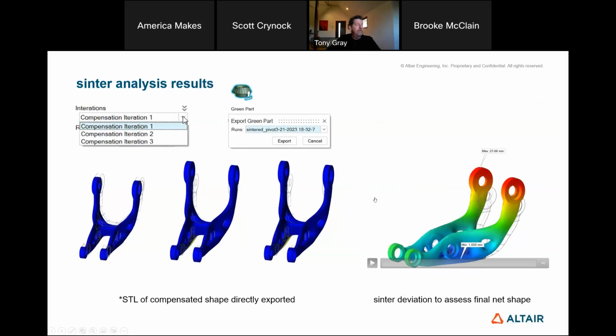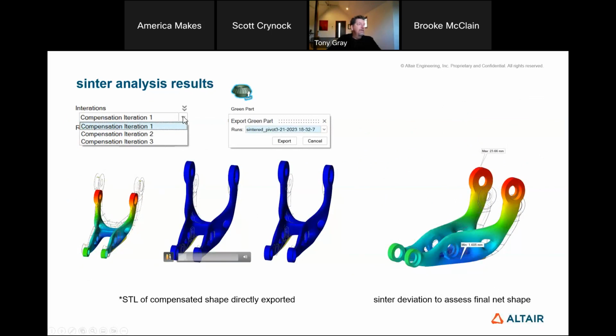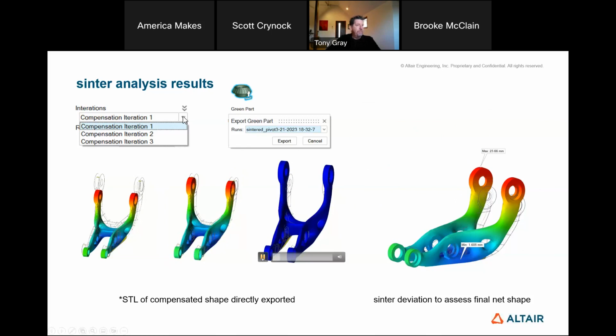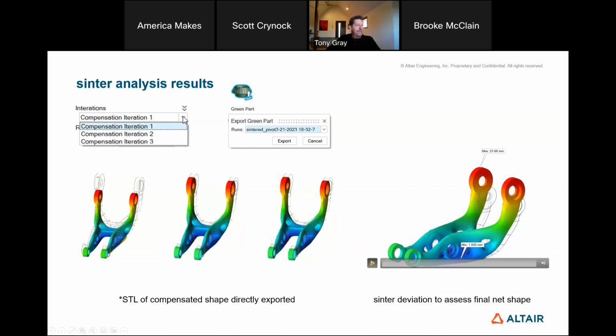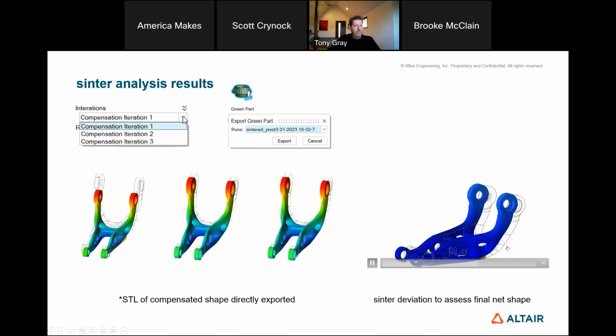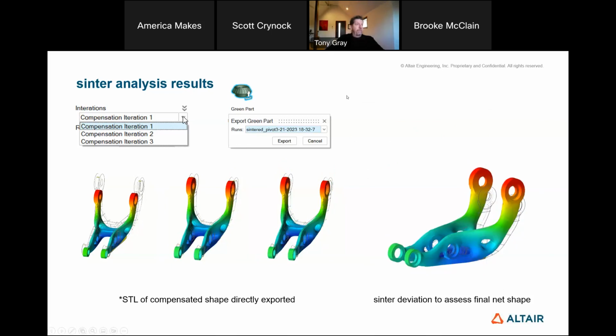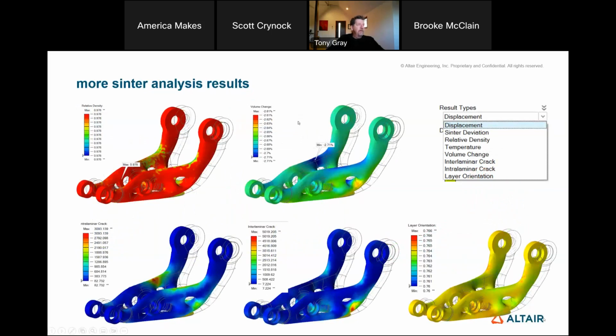After running this, it did 3 compensation runs. You can see the first one starts off at some nominal size and then it shrinks down. The second one starts a bit bigger and it still shrinks past. And the third one gets pretty close to the final part. You can see the reason it's not lined up here is that it's actually shifted along on the print bed. So some more results: there's relative density, volume change, interlaminar crack, and layer orientation. So they can also be assessed.